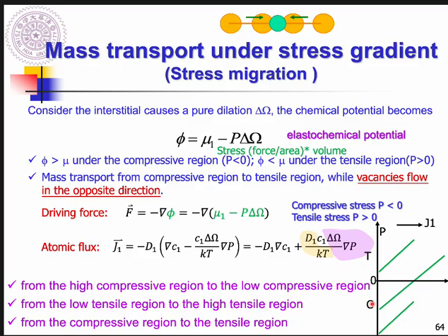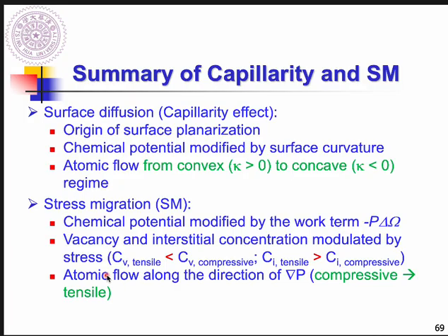You use a positive term minus a negative term, so you get a positive. Positive means moving to the right-hand side, the same direction as atomic flux, which means along. This small negative minus a larger negative also gives a positive. So this is why they mean along. Okay, so atomic flow is along the direction of the stress gradient. Okay, we end here. So we close lecture 2.